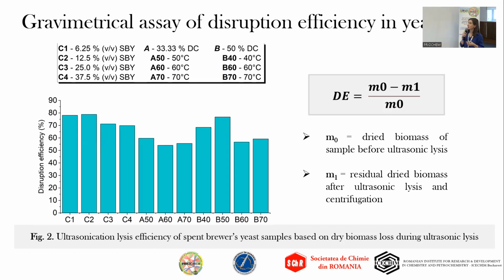We decided to test an additional assay method for lysis efficiency. So disruption efficiency was assessed using a gravimetrical method, which quantified the loss of dried biomass during lysis. This data confirmed the previous results, showing that there is indeed an inversely proportional trend between sample concentration and temperature. The lysis efficiency decreases with the increase of temperature and with the increase of sample concentration.